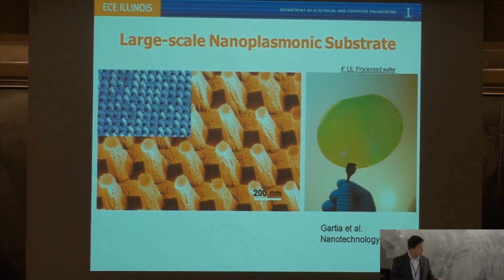All right, here's an example showing we can make a silicon or silicon dioxide nanopillar array with a very high uniformity, and you can then deposit metal. This is probably after metal deposition. You see those metal deposit on the surface.